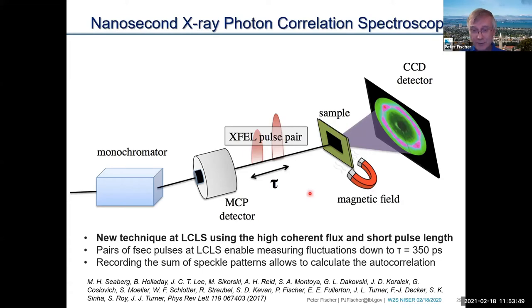And particularly we used a new technique at LCLS that not only uses the coherent flux and the short pulse length, but uses a pair of pulses. It's called the two-pulse XPCS technique. What it does is you hit the sample with the first femtosecond pulse, and then shortly after this, and you can vary the delay time, you hit it again.